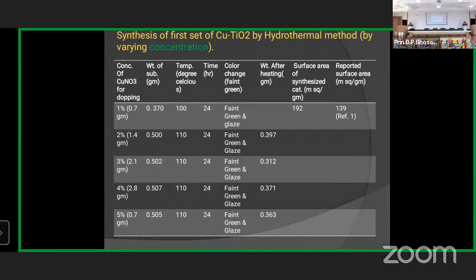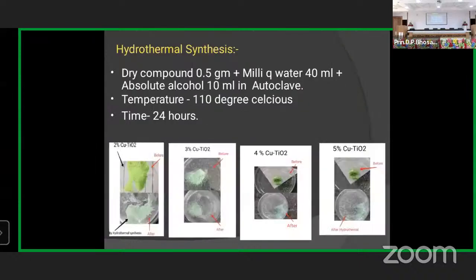The second column shows the weights we got. After that, the temperature we maintained for this preparation, then the time, which is 24 hours, and the color and the amount of the product after heating. The remaining tests we are going to do, but for the first 1% sample, the surface area we got is 192, and the reported surface area is 139 only. This is a very good thing for us, that we got a better surface area than the reported. Then these are some pictures of the samples I prepared by the hydrothermal method.